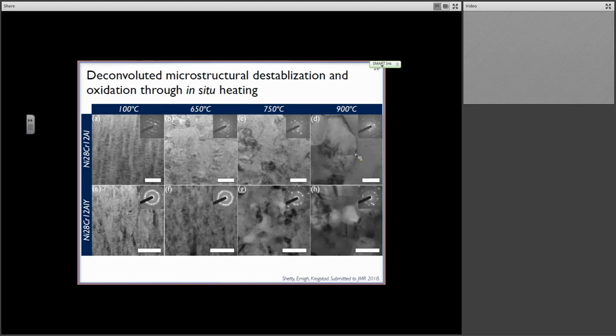And by the time we get to 900 C, the alloys without yttrium are very coarse. And we have fully equiaxed structures at 900 C down here with yttrium, but they're much smaller. Okay? So even without oxidation, even without that driving force, the yttrium is still playing a significant role in the way the microstructure is changing, which gives us some hint as to how the microstructure is influencing the oxidation behavior too.